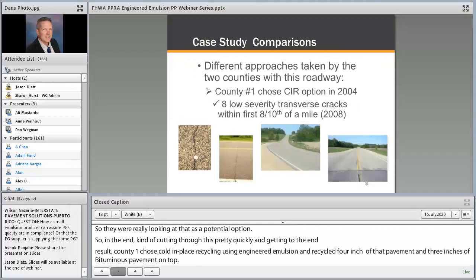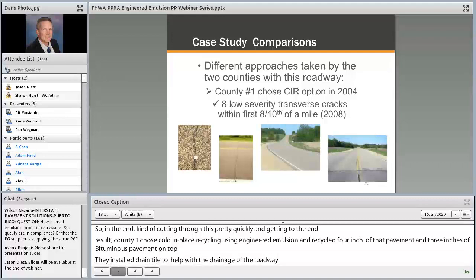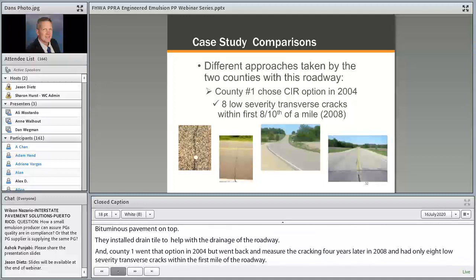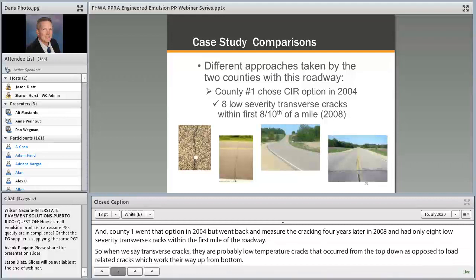And County 1, with that option in 2004, went back and measured the cracking 4 years later in 2008 and had only 8 low-severity transverse cracks within the first 0.8 of a mile on that roadway. And when we say transverse cracks, they very well are probably low-temperature cracks that occurred from the top down as opposed to load-related cracks which occur from the bottom and work their way up. And so when you're selecting a cold-in-place recycling process using engineered emulsion, you want to make sure that you select a good PG binder that's crack resistant on top too, to avoid any of that top-down cracking that might occur.